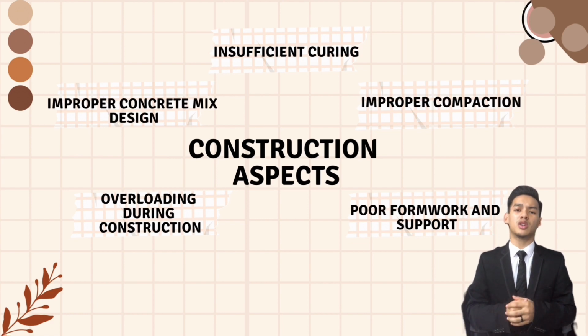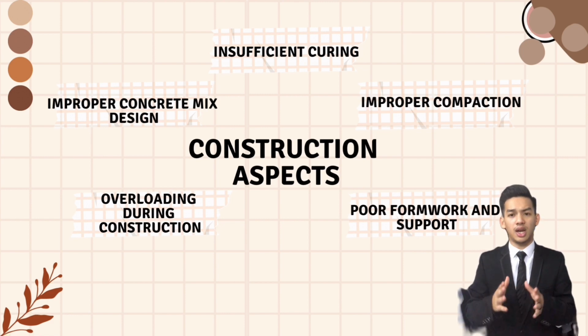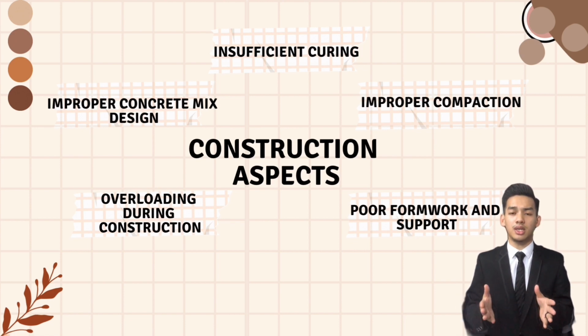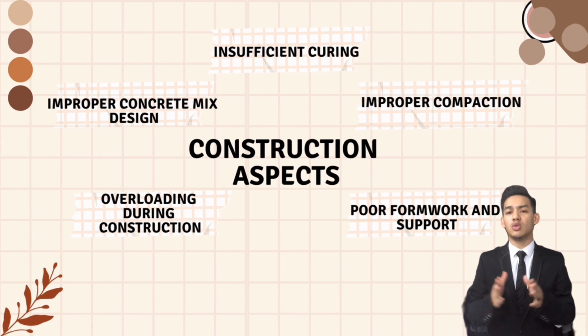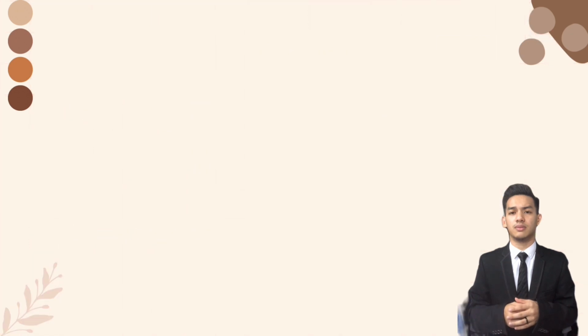Besides that, improper compaction. Concrete not properly compacted during placing may develop voids, honeycomb, poor consolidation. Other than that, is overloading during construction. During construction, high loads on the slab, such as the storage of bulky construction supplies or heavy machinery, can lead to overstressing and cracking. Then poor formwork and support. The formwork might bend under the weight of the concrete if it is not sufficiently supported or braced, leading to an uneven or weak slab that is more likely to break.